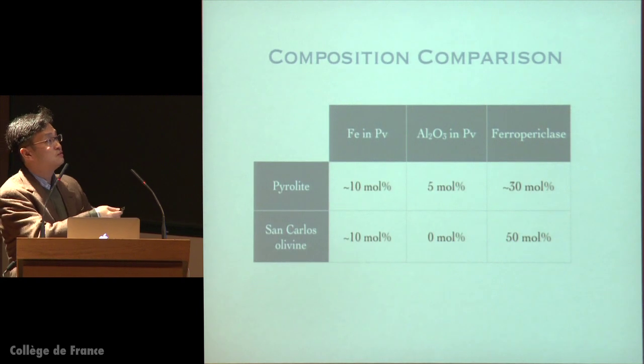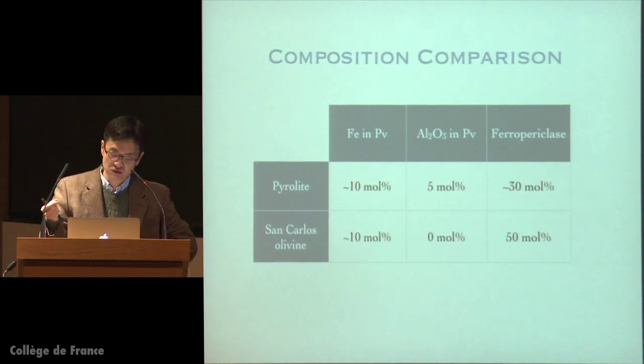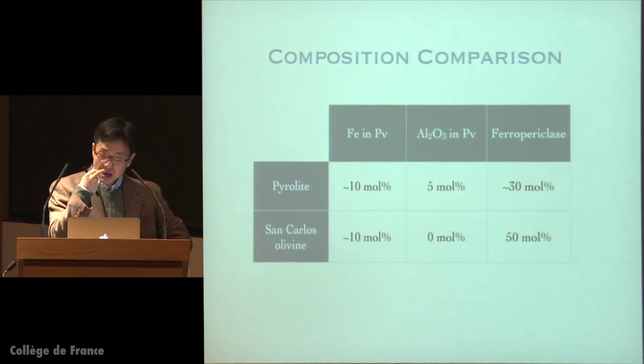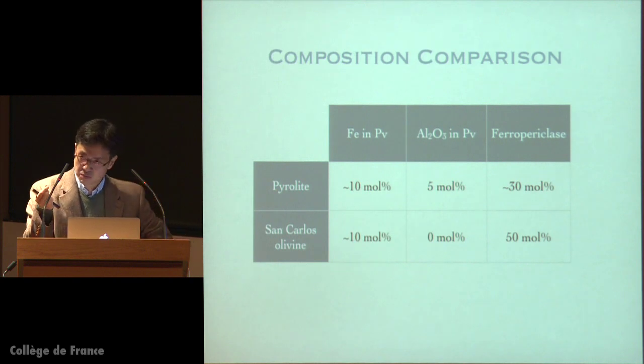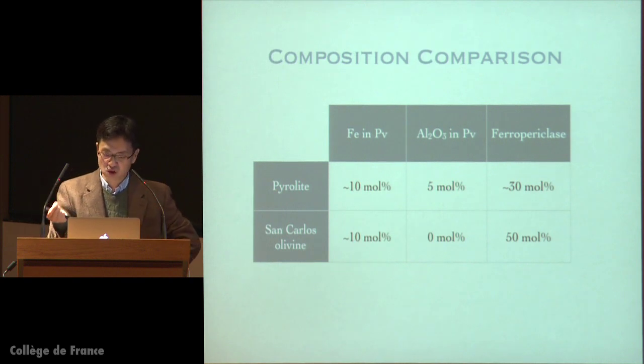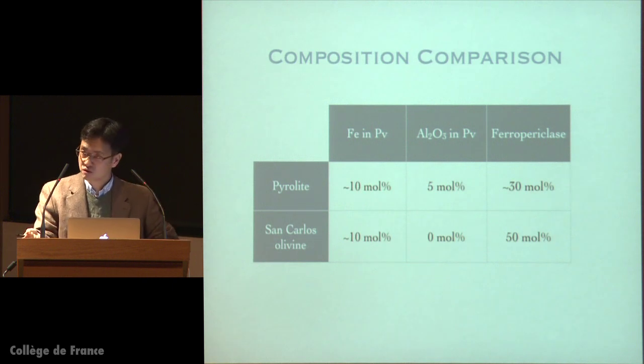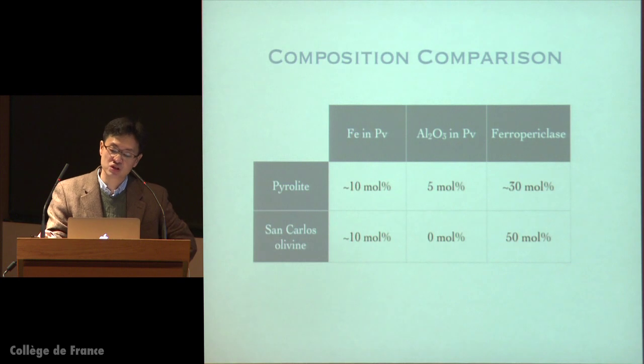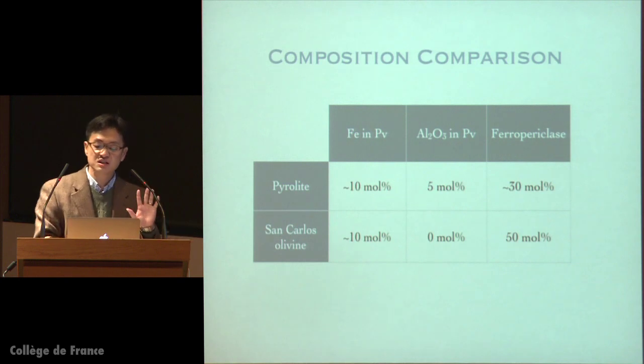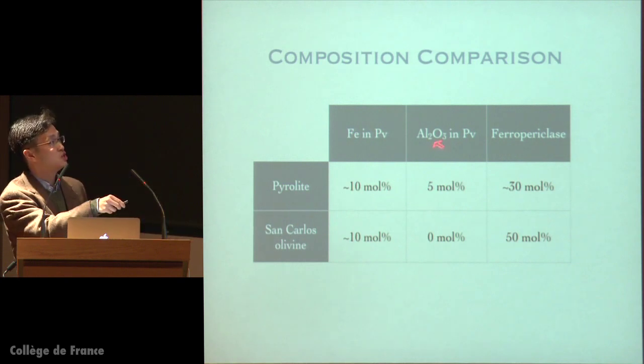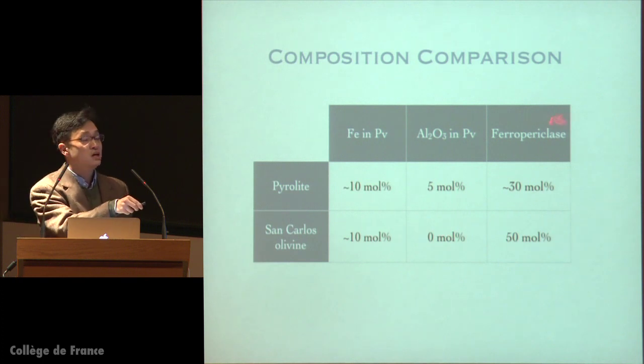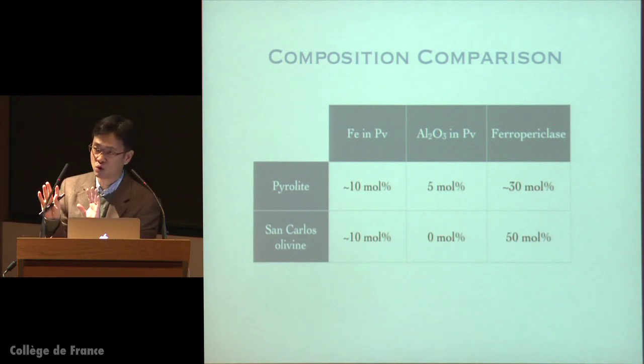And in terms of ferropericlase generation, pyrolite is supposed to generate about 30% from the system in the lower mantle. San Carlos olivine composition produces 50 mol% of ferropericlase. So now you can see the contrast between these two compositions in terms of aluminum compositions and ferropericlase. So those are the two important factors.